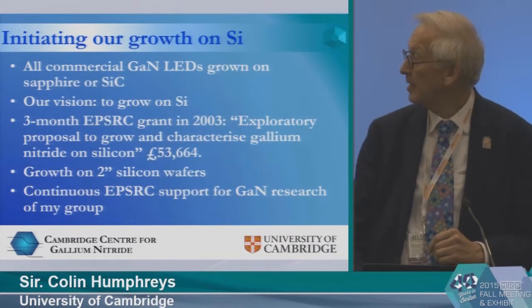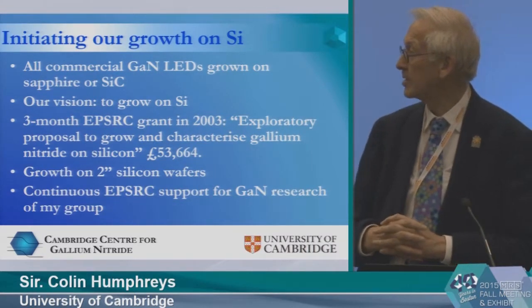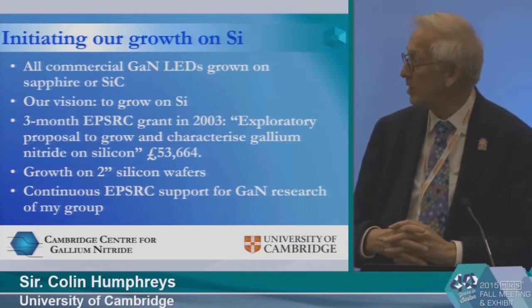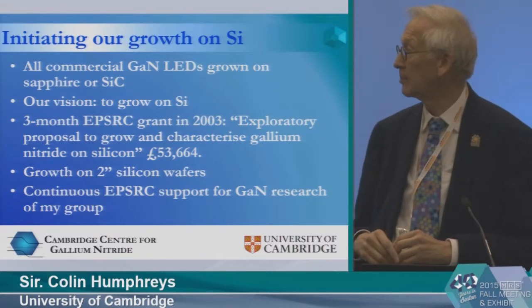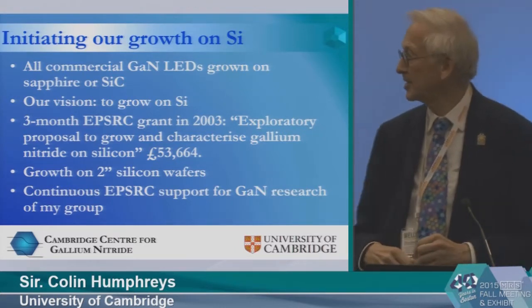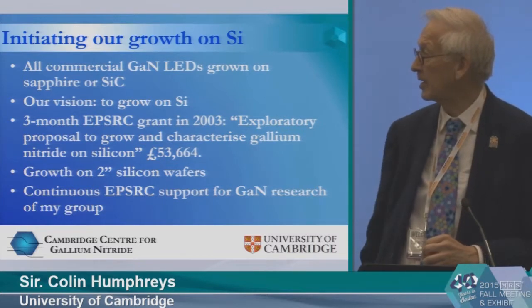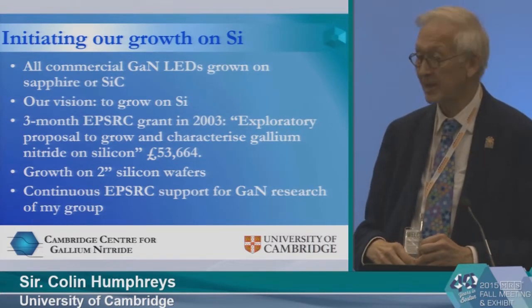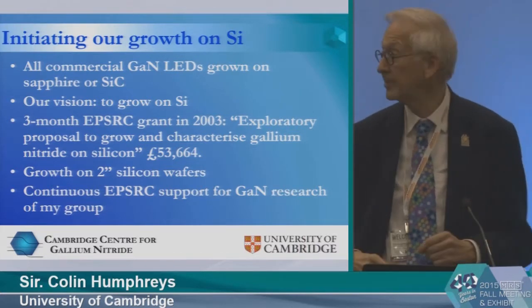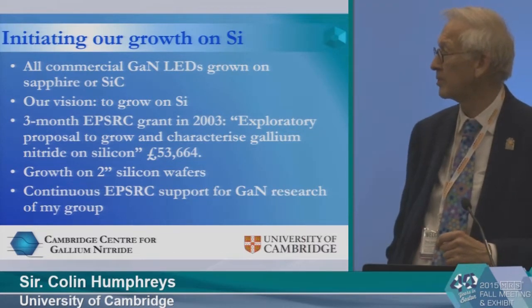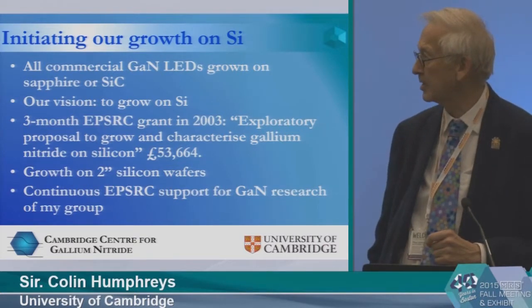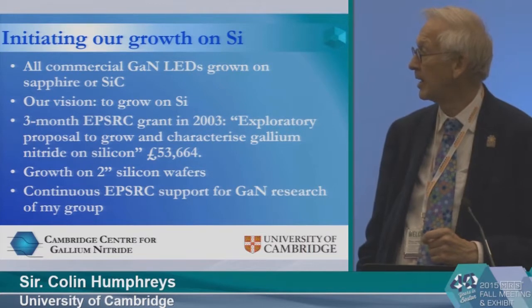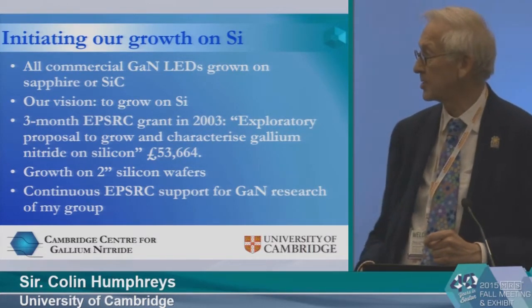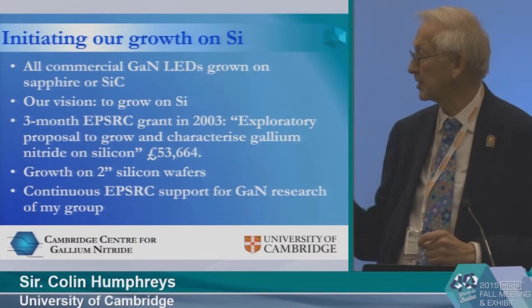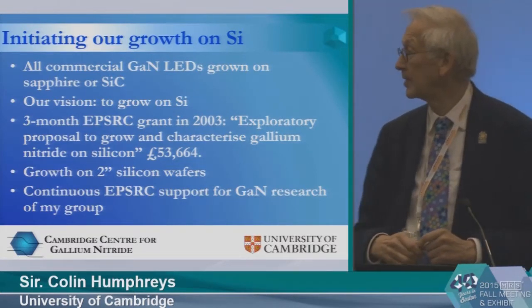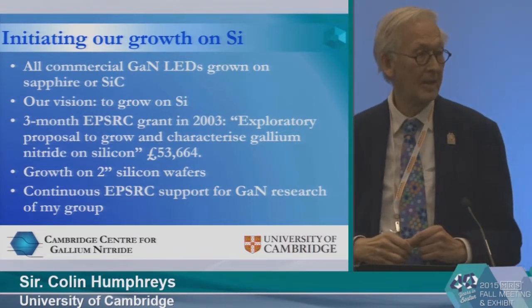Just to initiate our growth on silicon: when we started this work, all commercial gallium nitride LEDs were grown on sapphire or silicon carbide. Our vision was to innovate and to grow on silicon. It all started with a 3-month exploratory grant I had in 2003 from the EPSRC, the UK Government Funding Council, called Exploratory Proposal to Grow and Characterise Gallium Nitride on Silicon, and it was just over £50,000. That's how everything started, and we grew on 2-inch diameter silicon wafers then. I'd like to thank and acknowledge the EPSRC for continuous support for my gallium nitride research since then. And that's really important.